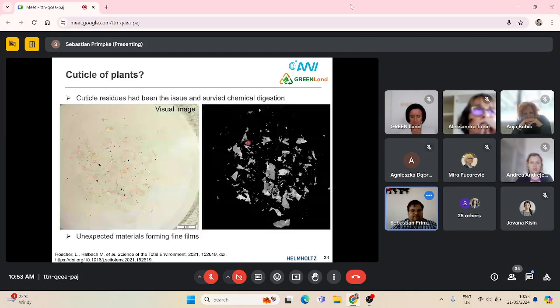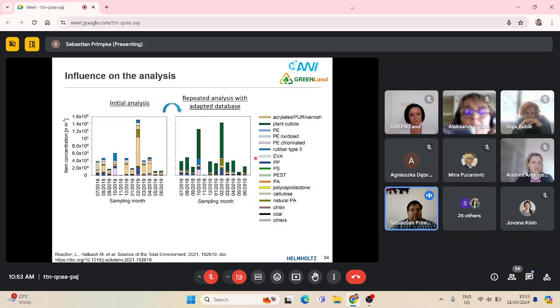And what was the impact? It was rather large. You now see that with the same data analysis, all these fine films are definitely identified as plant cuticle. Still, we found varnishes as well and other polymers, but you see it had a high impact on our numbers. The sample with the highest concentration of microplastics still had the highest concentration, but it was significantly reduced, by almost half or even more. But each of the other samples was affected as well. Still, we found most of the polymers in similar numbers, but for example this acrylates cluster in much lower numbers.